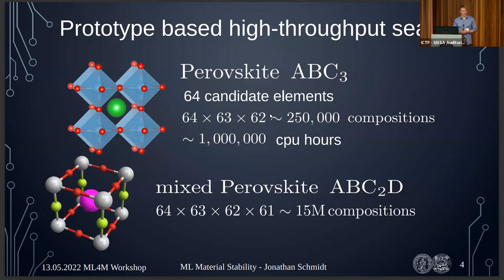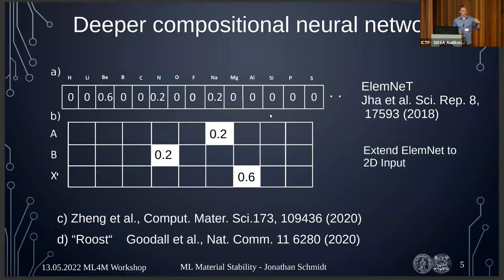But if we want to do this with thousands of ternary prototypes, it becomes really expensive. For quaternaries, we're already at 15 million compositions, so we can't really do this anymore. What people have been doing for the last seven years or so is machine learning: predict all the distances to the convex hull with a machine learning model, then just validate the ones closest to stability. Early models, maybe five years ago, used handcrafted features, decision trees, and kernel regression for a single prototype.